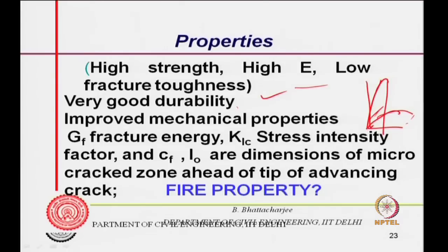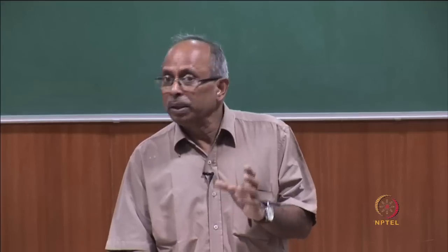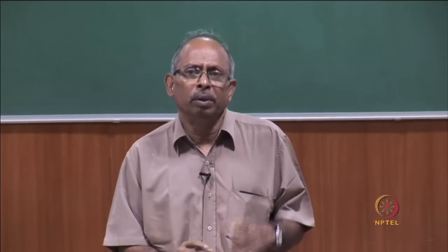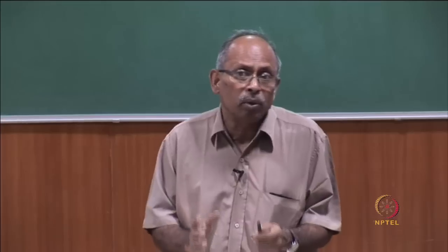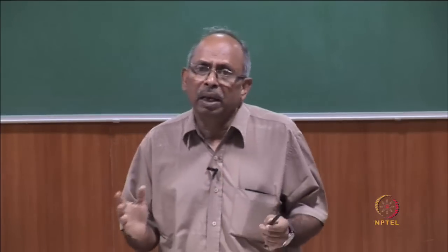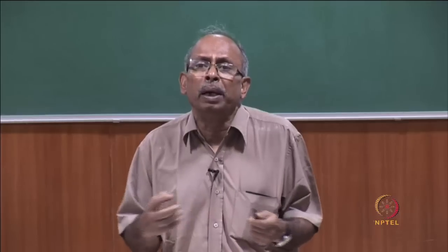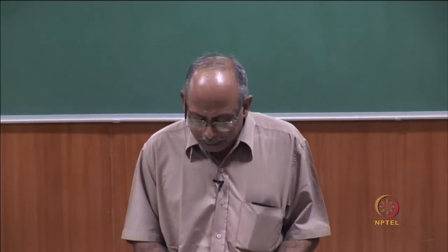Very good durability, because of low porosity, nothing can enter. But one must watch out for magnesium sulphate, because magnesium sulphate can attack the CSH itself. So, it is still good against all other sulphates, all kinds of durability issues, because of its strength, it does not allow anything to penetrate through it. Improved mechanical properties.